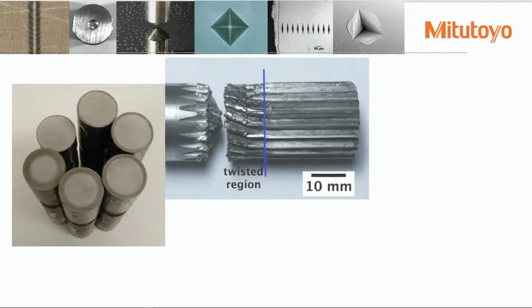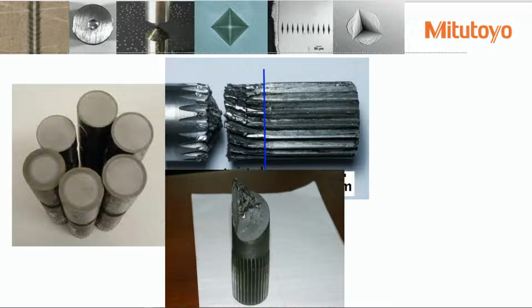Okay, well, the next picture shows this is a ductile failure. The part wasn't heat treated enough. It wasn't strong enough to support the amount of torque that was going in there. So they probably had a real thin case on that. Okay, the next picture shows the same type of shaft. That's a brittle failure. It broke because you can see the case on that looks like it's almost a 1/4 inch thick, and the part was just too brittle to work in its application.